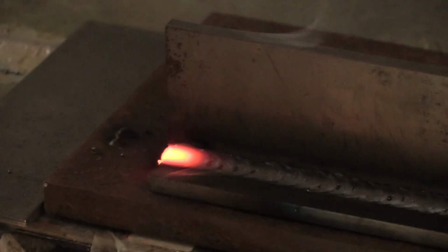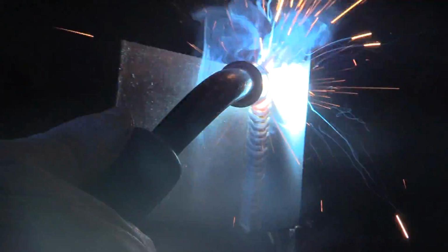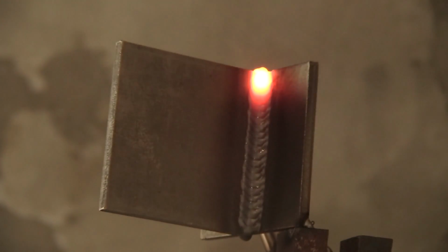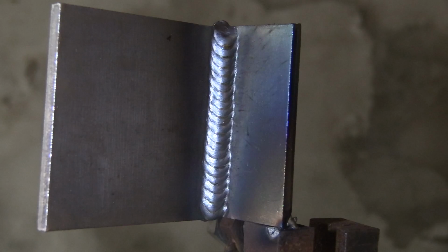Then I used the auto set function to run a standard fillet weld, a T-joint fillet weld. Also experimented with using the auto set function but just dropping down a couple of thicknesses for a vertical uphill weld, and found out that was kind of a trick. Instead of just figuring out settings, just drop down a couple of thicknesses but still use the auto set. Worked out really good for vertical uphill.